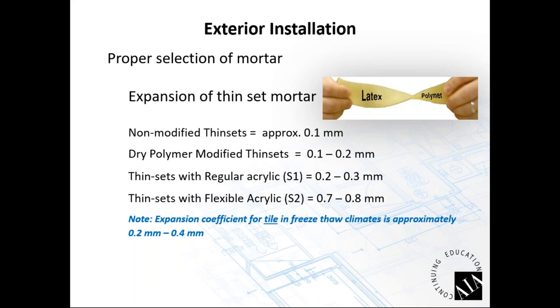When we look at your dry polymer modified mortars, these take a polymer that's been dried out, added into a bag of your sand and cement, and then at the job site, they'll add water to it. And again, making a polymer modified mortar, it complies with ANSI 118.4. The biggest thing is the amount of movement that you're getting out of that type of mortar. It's a very minimal movement. Will it hold your tile or stone to the substrate? Sure. How long will it hold there? Depends upon movement and climate change, how your building is being affected by expansion and contraction from heat and cold. Not the best mortar to be using on that type of application.